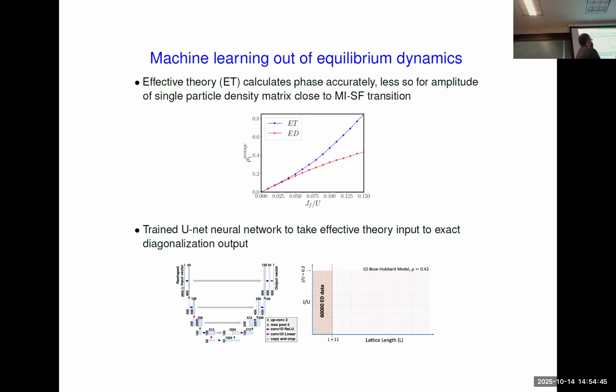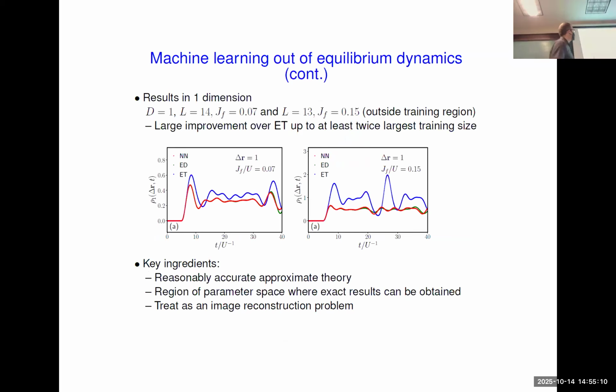We fed in the effective theory and trained our neural network to figure out what adjustments it needs to make to this result to get here. And it's not just adjusting the amplitude, it's actually trying to adjust both the amplitude and phase. And I'll show some results here. So in one dimension, we can actually do exact diagonalization to slightly larger than L equals 11. So outside the training region, L equals 14 and L equals 13. Here in blue is our effective theory, and you can see that the neural network results lie very close to the exact diagonalization results, even outside the training region, which we're pretty happy with.